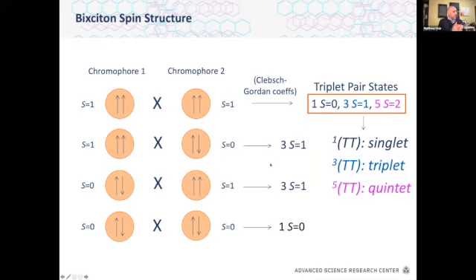Maybe slightly less familiar is this idea of what happens when you try to form 4 spin states. You can do the same thing. You can do angular momentum addition of 4 spin-1/2 particles, or you can just take the combinations of the products of the 2 spin states. So we can have a triplet exciton coupled to a triplet exciton, a singlet coupled to a singlet, or singlet coupled to triplet in various ways. And then you get a new manifold of particle states. And the ones we really end up caring about in terms of the spectroscopy are the triplet pair states, the ones formed from 2 spin 1 particles, mainly because they tend to be the lowest in energy. And so in terms of affecting the dynamics of the systems, those will be the ones that, again, have the most relevance for determining the fate of the carriers as a function of time.